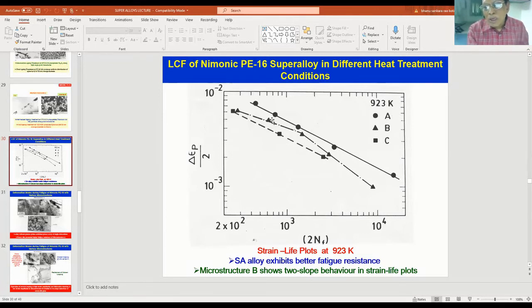What will be happening for the solution annealed material? You see that the fatigue resistance is quite good. For microstructure B in the peak aged condition, look at that, the fatigue resistance is decreased, and the overaged condition gave you poor fatigue resistance. But see, in the case of B, what is happening there?